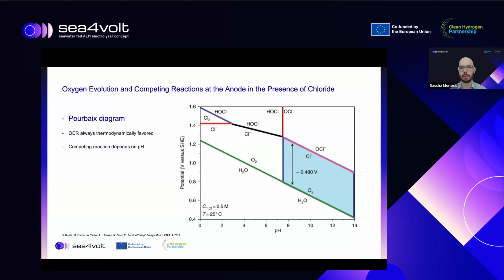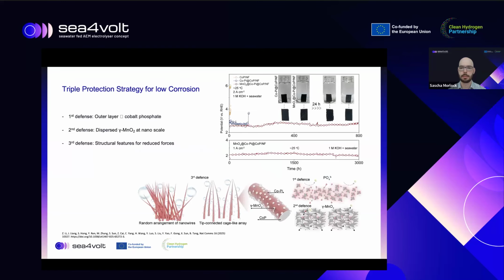However, a side reaction is possible if the overpotential for OER is too high. And depending on the pH, we see different side reactions, which is especially critical for low pH, because we have chlorine evolution, which is possible below a pH of about 2 or 3. And we also need only a very low overpotential to achieve that undesired chlorine evolution. So typically we go to higher pH values, where you have about 500 millivolts until we see this side reaction. Next slide, please. So different strategies have been exploited.